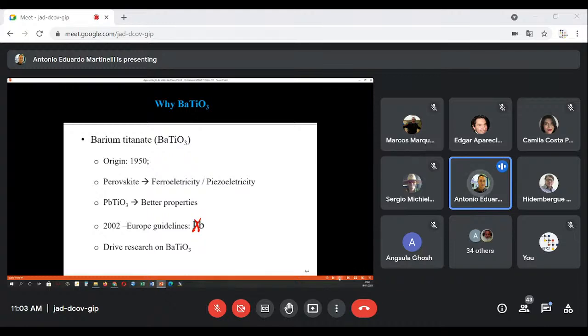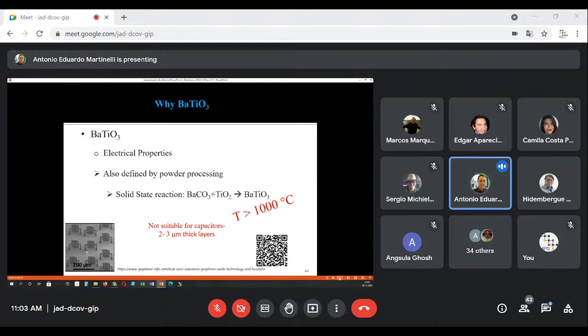So we chose barium titanate. It's a well-known material. It has a perovskite type structure with ferroelectricity and piezoelectricity properties. Actually, lead titanate has better properties, but from the beginning of the 21st century, following European guidelines, lead cannot be used anymore. So this drove the research on alternatives to lead titanate, and barium titanate is the most important one. The electrical properties of barium titanate allow its use, for example, in capacitors.